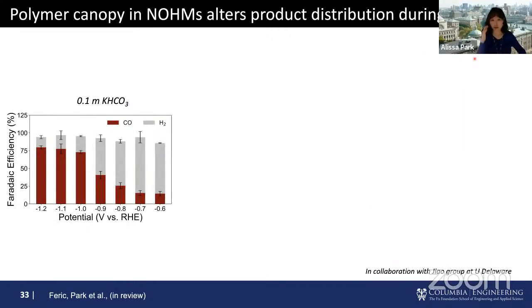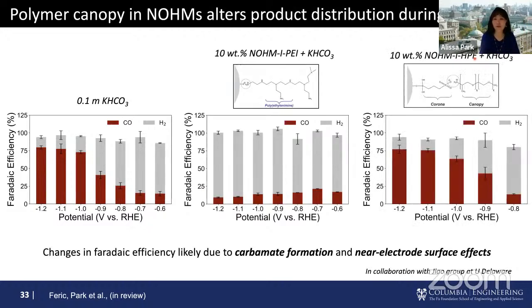Now we just have to do the electrochemical conversion of the CO2 loaded into these different electrolytes, and we were collaborating with Feng Jiao's group at University of Delaware. We started with just potassium bicarbonate electrolyte, no NOHMs, and compared that with two systems, one with PEI-based NOHMs and the other with HPE-based NOHMs. So this is physisorbed CO2, and this one is chemisorbed CO2. Looking across the different potentials, there's always competition between hydrogen evolution reaction and CO2 reduction, and it's very typical data. You can see that the PEI-based NOHMs electrolyte is very different, compared to the HPE-based one, which is somewhat similar.